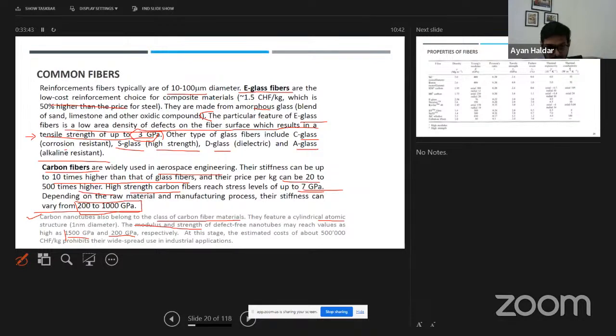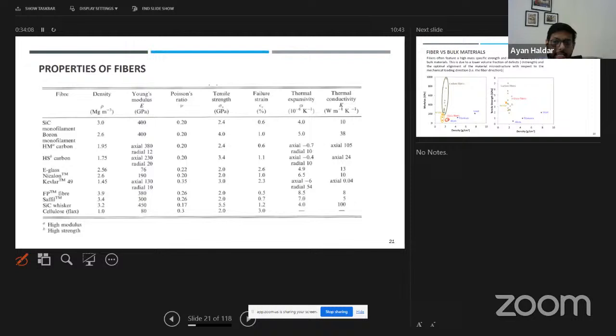We are now in the era of 3 gigapascal or 7 gigapascal, but these kinds of structures offer a huge leap. You can get about 200 gigapascal of strength, which is enormous. But obviously they are quite expensive, and therefore quite limited in current industrial use, right? This is the table that I was talking about. If you see here, this is high modulus carbon, where the strength is about 2.4, and this high strength carbon is about 3.5.